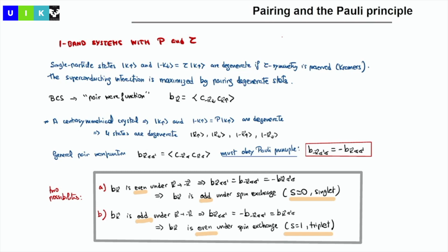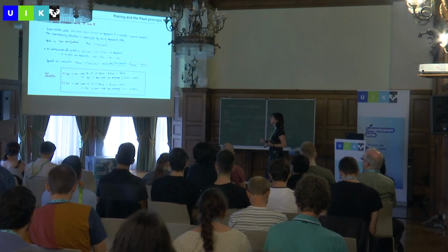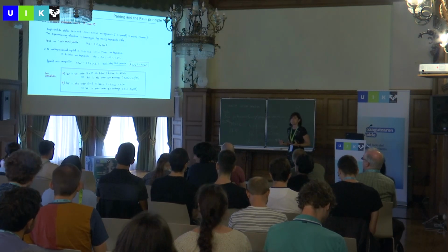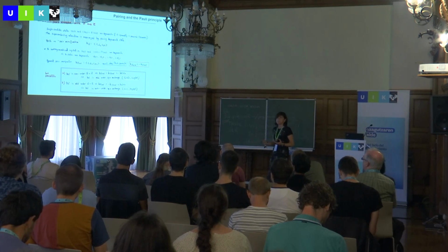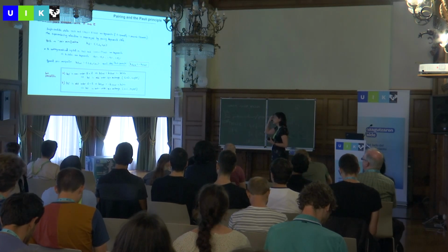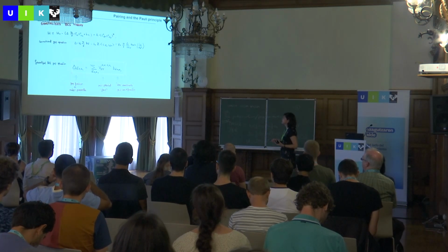So that means if this condensate is even on k to minus k, then because of the Pauli principle, this should be odd on the spin exchange, so I will expect to have a singlet Cooper pairing. On the other hand, if this condensate is odd under the transformation from k to minus k, then enforcing the Pauli principle, we expect that this Cooper pair is even on the spin exchange, and we may expect spin 1 triplet states. So we see already, by playing with the symmetries of the system, we get a lot of information about the symmetries of the order parameter that we expect for our Cooper pair.